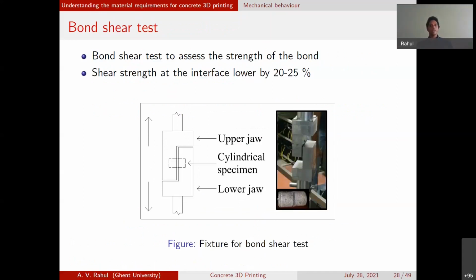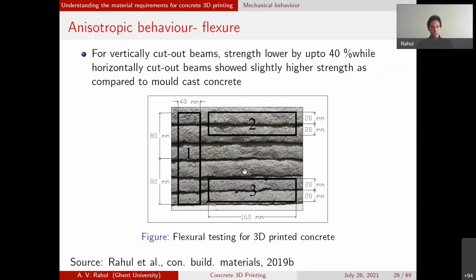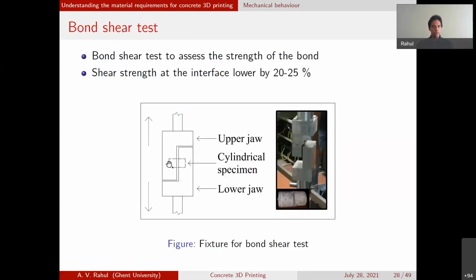So how do you characterize the interface properties? Because interface properties can, as we see in the earlier slides, significantly influence the mechanical behavior. So one way to do that is to do a bond shear test. You can cut out cylindrical specimens with the bond existing at the center. And then if you do a direct shear like this, pulled from both directions, and cause a failure to happen at the interlayer, you can characterize the shear strength at the interlayer.